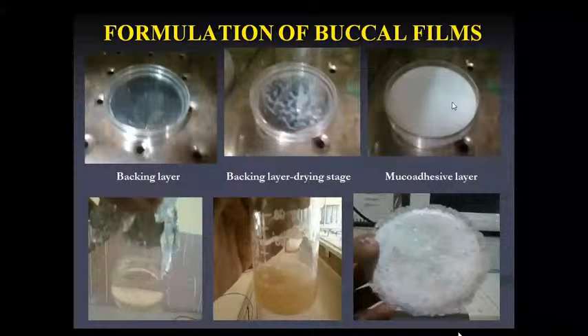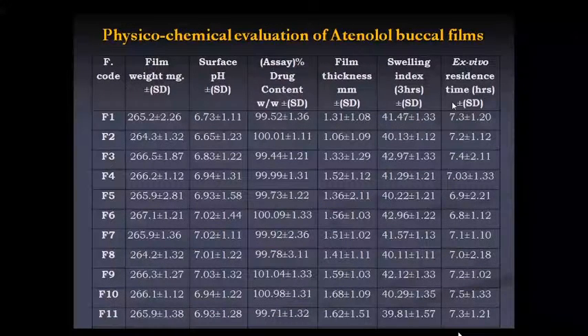All right. So after the manufacturing of the film, as usual, like tablets, we need to do all the quality control tests for the film as well. So film weight, the drug content, thickness, these are all the common usual tests. But here, if you look, the surface pH, swelling index, and ex vivo residence time are quite unusual when compared to the tablet quality control tests. So what is that? Why do we need to do these tests?